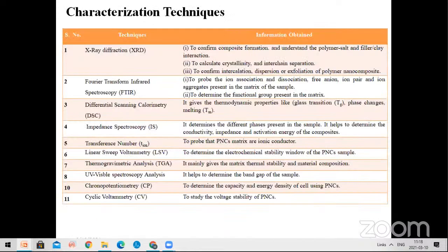And we use several techniques to characterize these polymer electrolyte films. First one is XRD. XRD is to confirm the composite formation, understand the polymer, salt and nanofiller interactions, and calculate the crystallinity and interchain separations. In XRD, we also confirm whether the nanocomposite is of the intercalated, dispersive, or exfoliated type. Another one is FTIR spectroscopy, to probe ion association and dissociation of free ion pairs in the polymer matrix, and to determine the functional groups present in the polymer matrix.